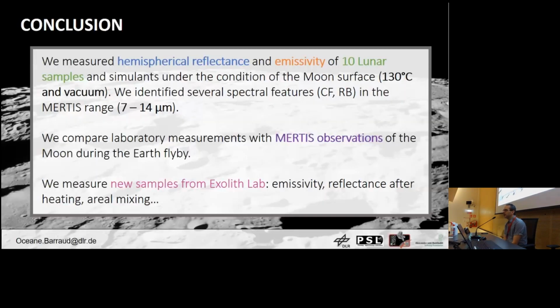So just my last slide on the conclusion. We measured hemispherical reflectance and emissivity of 10 lunar samples, and of course we are measuring them in emissivity under lunar conditions, so in vacuum and 130 degrees, and we of course identified several spectral features, the Christensen feature, the Reststrahlen band in this spectral range that we cover with MERTIS. And we are comparing the measurements with MERTIS.